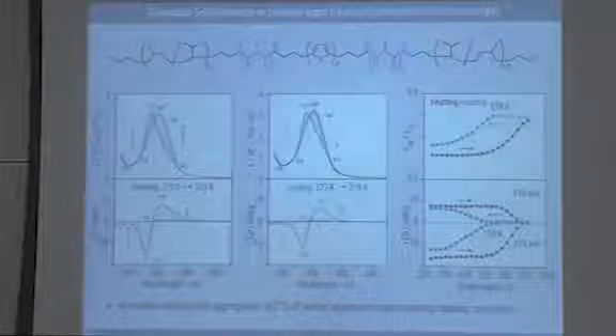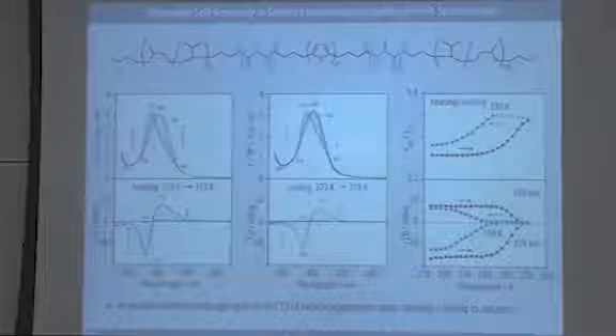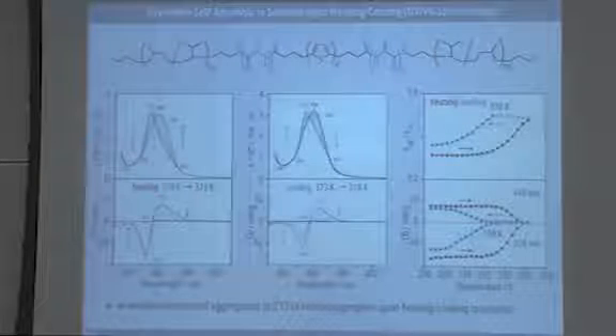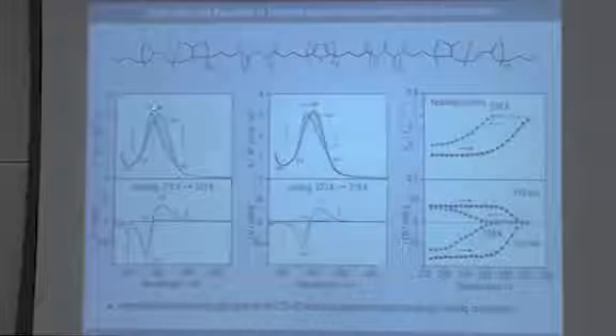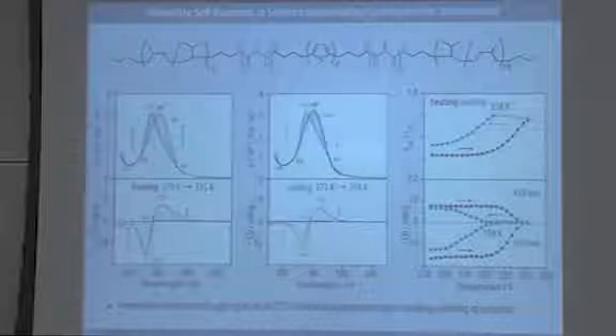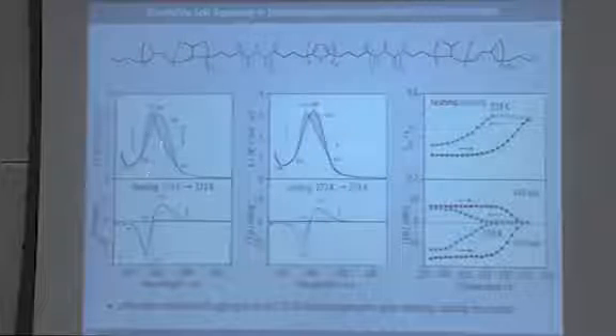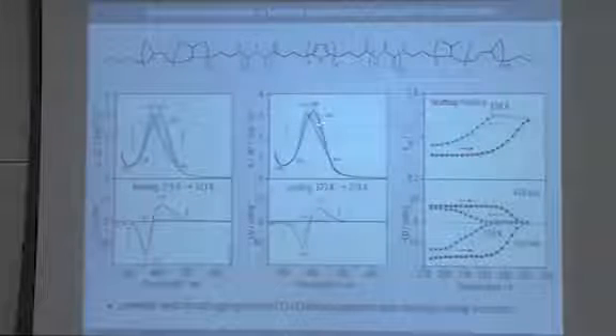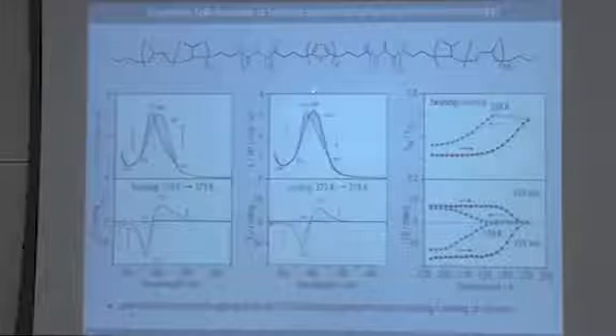Now, importantly, as I already mentioned from the IR spectroscopy, the aggregation in solution is thermally reversible. And this you also see in the UV-Vis and the CD spectra. So you take a solution containing the nanofibrils, and you heat the solution, and you convert the H aggregate peak into the molecular peak, and you cool the solution again, and you go back. So everything is nicely thermally reversible.